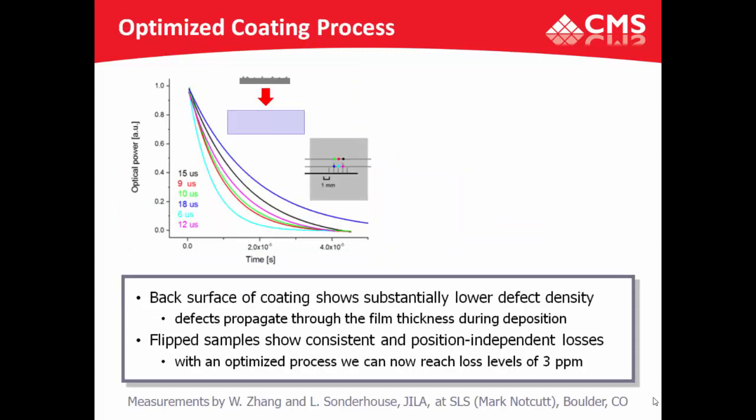So let's take one of those highly defective coatings. Note that every time these little crystallized bits embed in the film, the layer grows over them. This small bump propagates through that layer to the next layer. So any defect incorporated, any form of nodular growth, propagates through to the top surface, and now it's getting integrated from all the defects on the top of that plate.